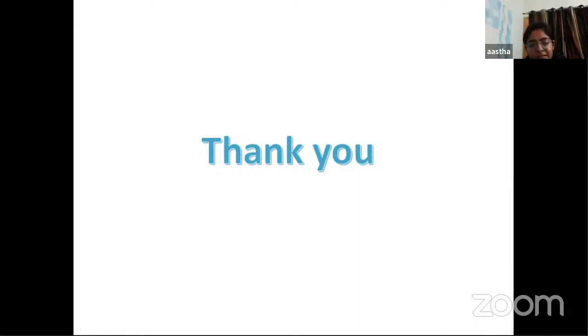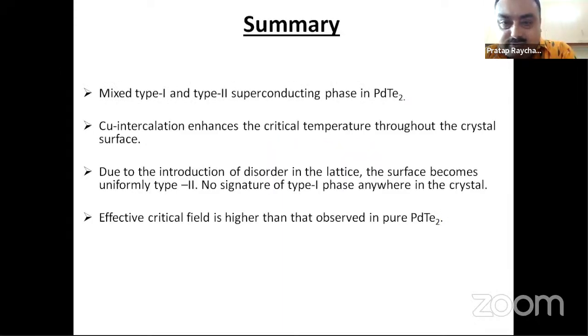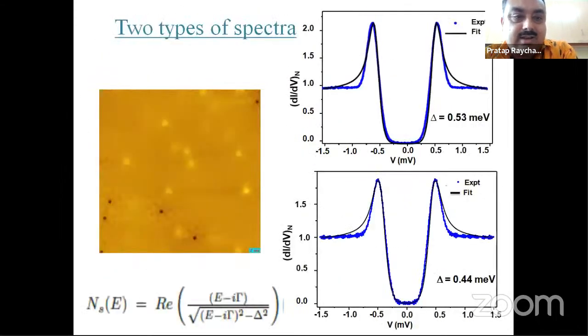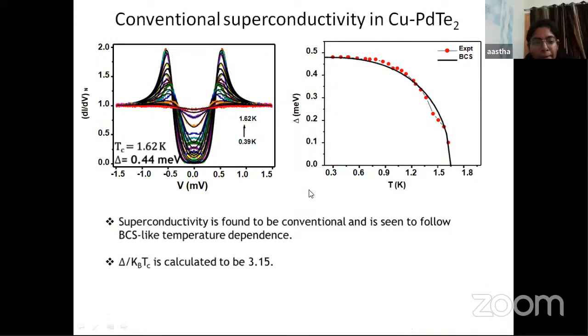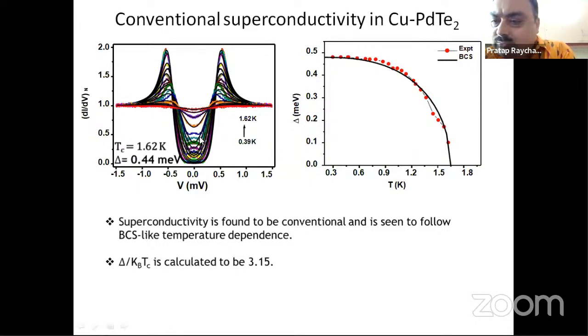Aastha, show your fitting. When you show the fit of your spectra, can you go back to the fit of your spectra? Next slide. Okay. Yeah, so you see the fit of your spectra, though you are showing it in a very crowded graph, it's actually very poor. At close to zero field, there is a large deviation, and close to the coherence peak also, the deviation is quite large. First of all, why is this deviation? And secondly, with such deviation, what is the reliability of the parameters that you are extracting?